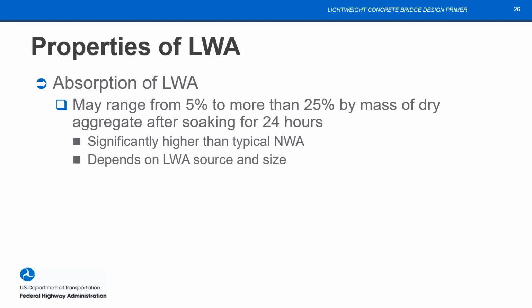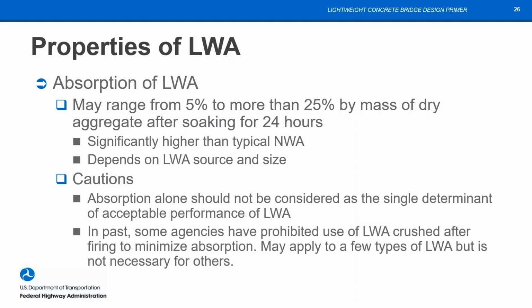Absorption is an important property for lightweight aggregate because lightweight aggregate is expanded and it has pores in it. Those pores or holes reduce the density of the material. The absorption typically ranges somewhere from 5% to 25% by mass after you soak it for 24 hours. And it does depend on different lightweight sources and size. But it is important that absorption alone should not be considered as the single determinant for acceptable performance.